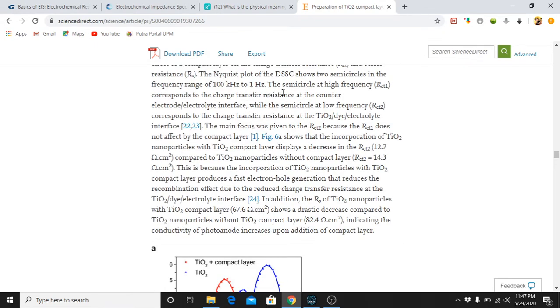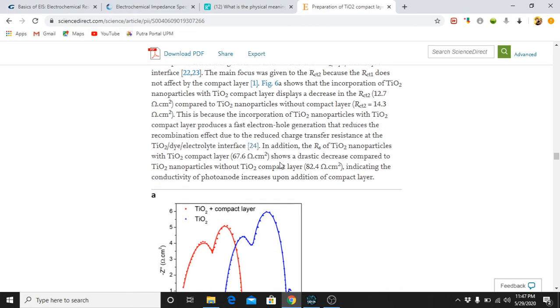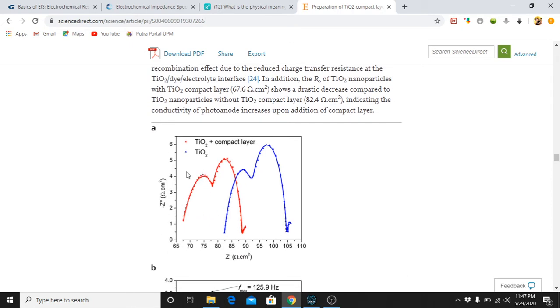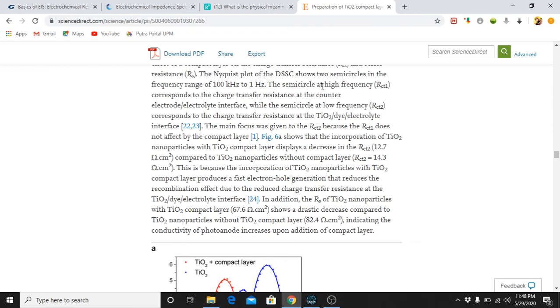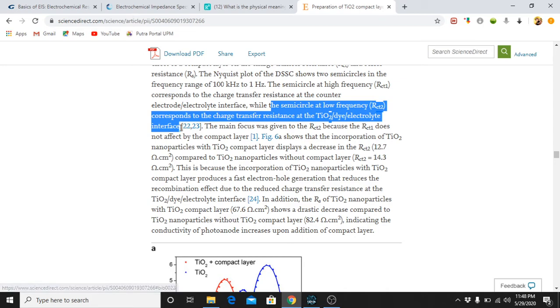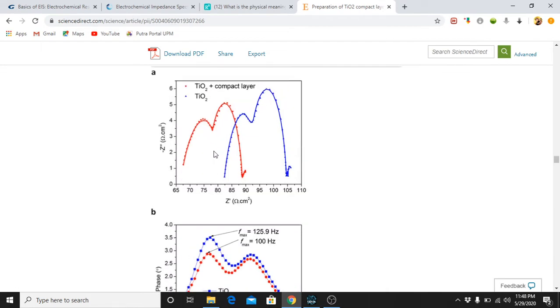Next, this paper explains what the semicircles at low frequency and high frequency are. The first one is the semicircle at high frequency. You could say the first one is located at low frequency, but actually it is vice versa, because the machine scans from high frequency to low frequency. So the first semicircle is at high frequency. The semicircle at high frequency belongs to the charge transfer resistance at the counter electrode electrolyte interface, while the semicircle at lower frequency belongs to the charge transfer resistance at the TiO2 dye electrolyte interface.